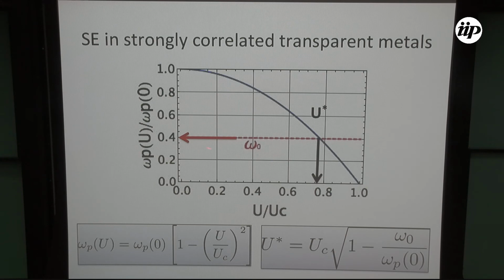So this is the curve for the plasmon frequency as a function of the correlations. And you see that it decreases. So imagine that I want to place inside this correlated metal an emitter that has a characteristic frequency that I've chosen randomly, for example here 40% of the value of the bare plasmon frequency. If I don't increase the correlations enough, I will be in the reflecting region, and I will put the emitter and I won't see anything. But if I keep increasing correlations, then I arrive at a regime where the plasmon frequency is smaller than the emitter frequency, and I can have a transmission. So I have hope of seeing something.